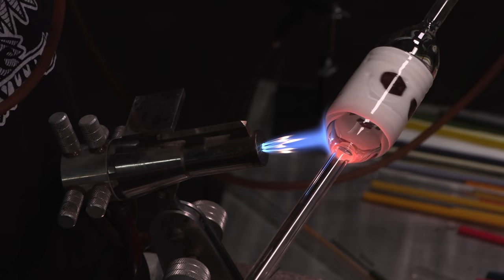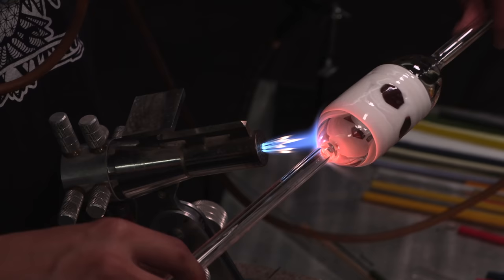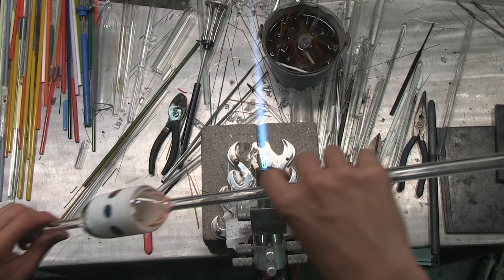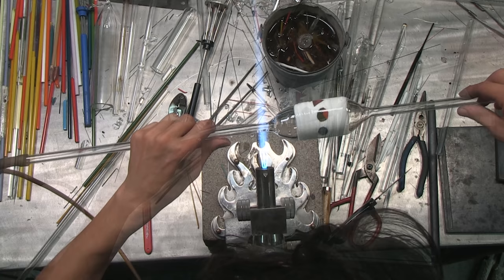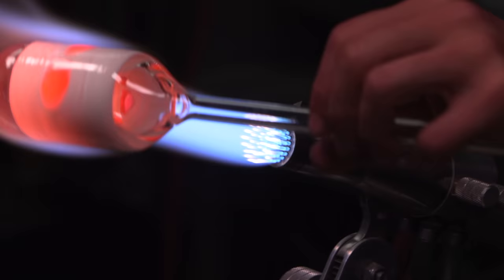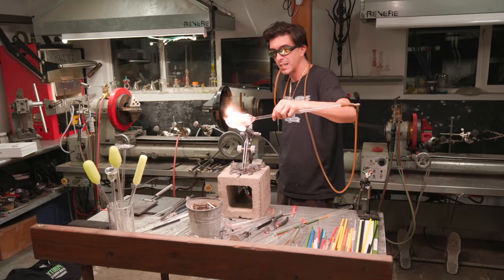As you saw when I was working with the marver, while I'm working this piece back and forth, it wanted to start condensing on me. It started to condense back and make a smaller cylinder. I've got my cylinder shape, and it wanted to condense back like you collect up a ball. If you just take a solid rod and heat it up, it starts condensing. So as it was happening, I angled myself and let it drip forward just a little bit using my hand paddle. So I'm still able to control what's going on, using gravity to my advantage while still marvering.